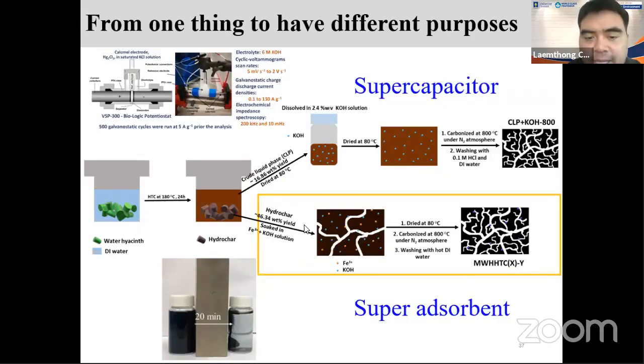But compared to the literature, we put in a very, very small amount of potassium hydroxide in comparison with the amount they put in the literature. We put in a little potassium hydroxide to precipitate the iron, and not only to precipitate the iron, but also to do the activation at the same time. For the liquid product, we do the activation as well, with a little potassium hydroxide. So in this system, I'm proud of the term zero waste. We have both liquid and solid, but we use both of them to make things.